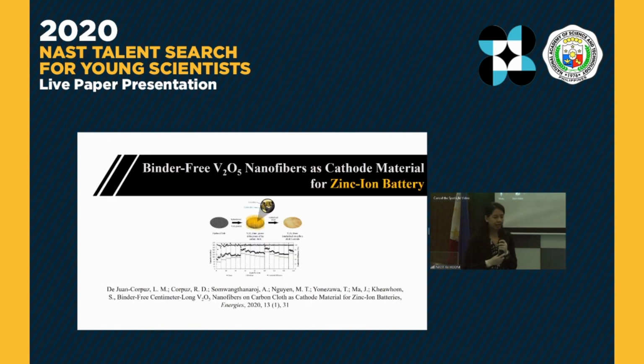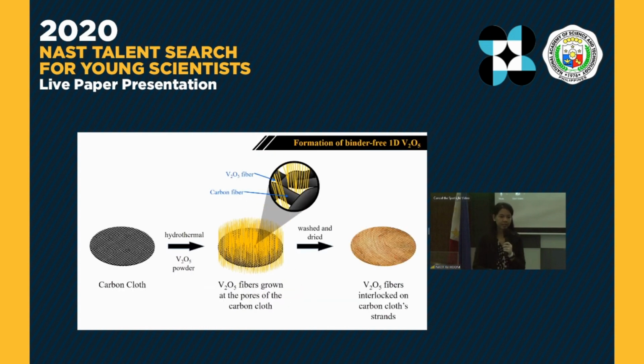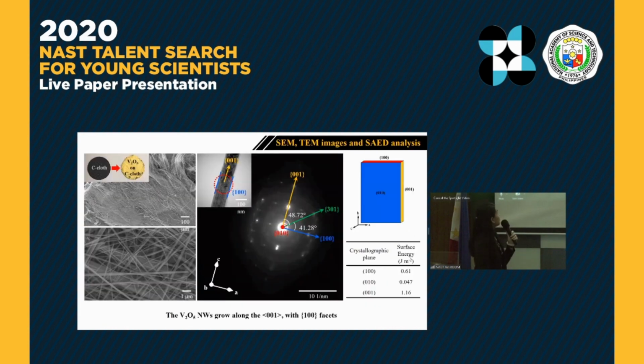For the zinc-ion battery, instead of using ZnV2O4, we utilize V2O5 nanofibers. In this synthesis, we utilize a binder-free V2O5 wherein we directly grow the V2O5 nanofibers on carbon cloth without the use of any binders. For this synthesis, based on our result,